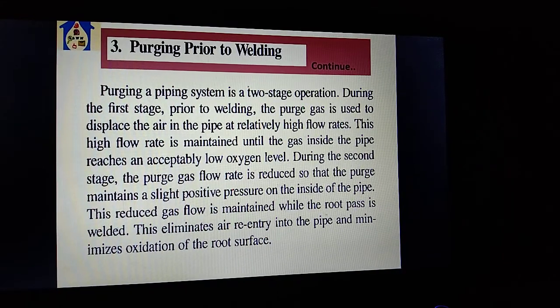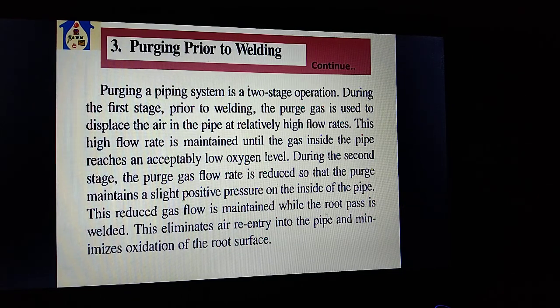Purging a piping system is a two-stage operation. During the first stage, prior to welding, the purge gas is used to displace the air in the pipe at a relatively high flow rate. This high flow rate is maintained until the gas inside the pipe has reached an acceptably low oxygen level. During the second stage, the purge gas flow rate is reduced so that the purge maintains a slight positive pressure inside the pipe.